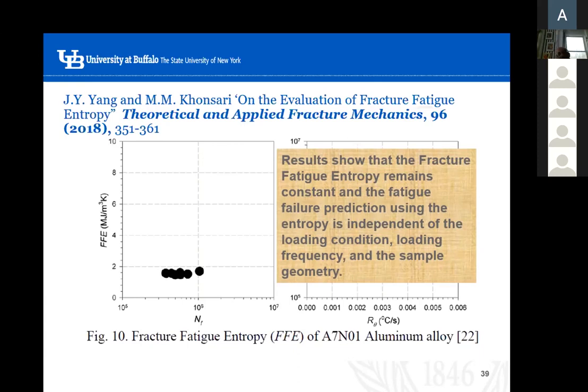Okay, sir. Understood your point. So may I just add, want to get one clarification. For example, your high cycle fatigue, which is basically a stress control. I'm talking mostly on the basis of test data, which clearly shows that the fatigue life is a function of the size of the specimen. You know, it's well proven. So if you take a thin rod and if you take a thick rod, the fatigue failures are very much different. I'm talking about high cycle fatigue. It's not applicable for low cycle fatigue. So high cycle fatigue damage is one of the functions of the size effect. So can you give some clarification on what you told?